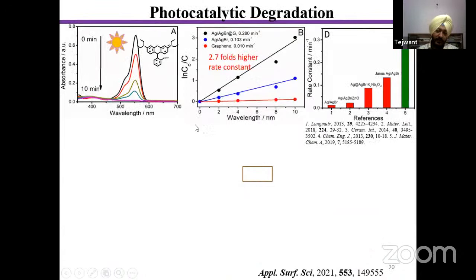So the prepared catalyst, which comprises graphene as well as silver bromide nanoparticles, has been utilized for photodegradation of rhodamine B under sunlight. We have compared the results with bare silver bromide nanoparticles. The presence of graphene along with the silver bromide nanoparticles has led to a 2.7 fold increase in the rate of photodegradation as compared to the bare silver bromide nanoparticles. In panel C, we have compared certain photocatalysts which have been earlier utilized for the photodegradation of rhodamine B. We have found that the composite nanomaterial prepared with the aid of surface active ionic liquid is almost thrice as active as compared to many of the reported nanoparticles.